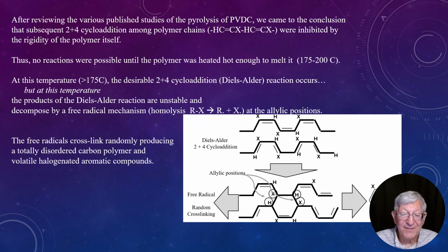And so using that as an intro, after reviewing the various published studies, and there are a number of published studies in both manufacturing and in scientific literature, of the pyrolysis of PVDC, we came to the conclusion that the subsequent 2+4 cycloaddition of this polymer, once you have lost 1 mole of HCl, you've got this polymer which has alternating double single bonds. And for reasons that were not clear in any of the authors' writing, it didn't happen at ambient temperature, which is kind of interesting because 2+4 cycloadditions frequently happen at ambient temperature. You usually don't have to heat them up. But for some reason, you had to heat this up to 175 degrees.